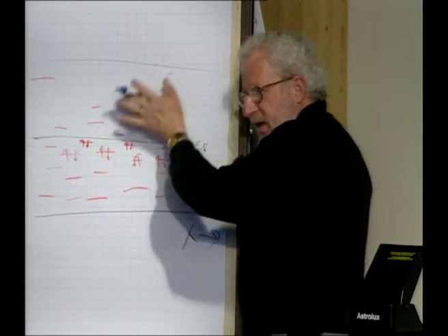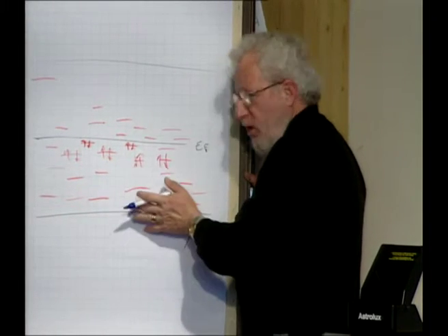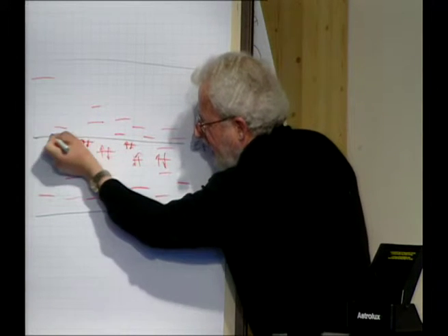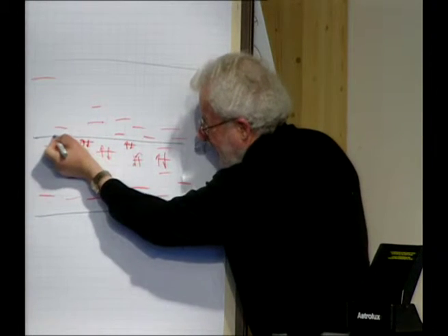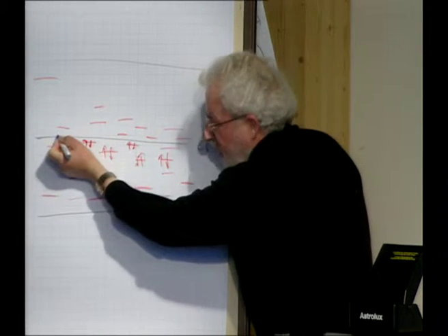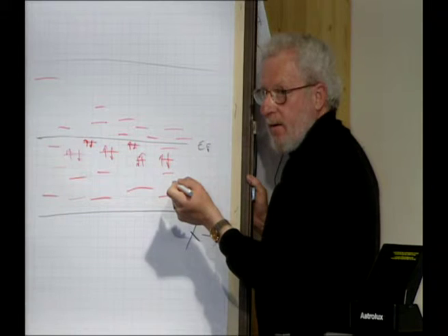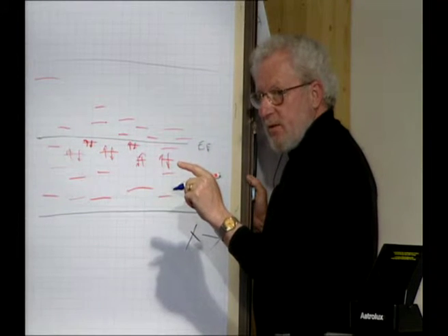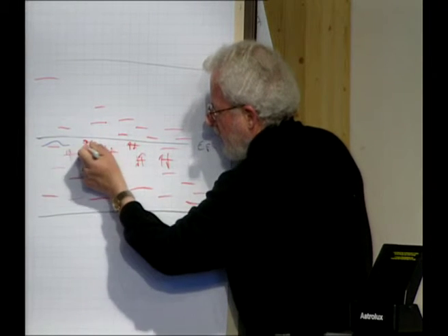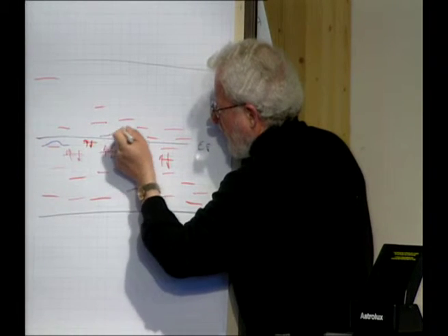And if you think about that for a moment, it's always true. You have a continuous density of states. They're all localized. If you go far enough away, you're going to find a state here that's infinitesimally close to the Fermi energy. So if you go far enough away, you'll find a state with zero activation energy. But the wave functions are localized. All these wave functions are localized.